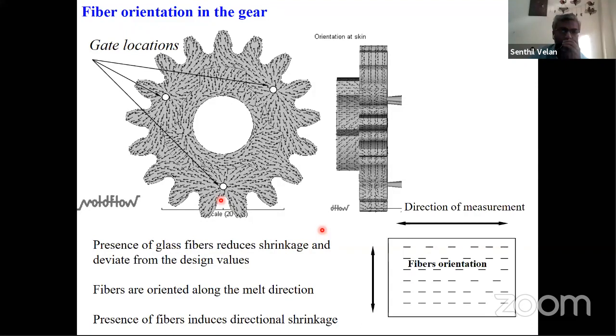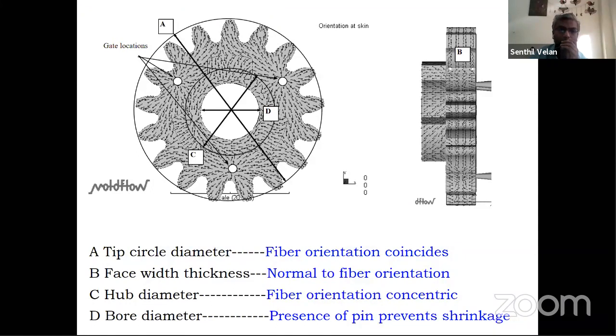So that means if you measure the outside diameter or the hub diameter, you are measuring along the fiber orientation, and in the face width direction you are measuring normal to that. Naturally, when you measure in these two ways, you will have a big difference as far as the shrinkage is concerned, because of the amount of material and the amount of fiber present here, whereas in this direction it differs. So this is really going to make a huge difference. This picture gives an idea about the two different things: this is your hub portion, and this is your tip circle diameter, where the fiber orientations coincide, whereas normal to the fiber orientation is your face width direction.